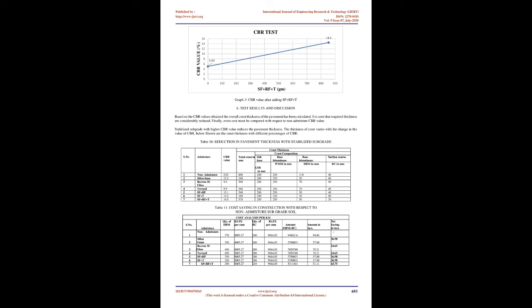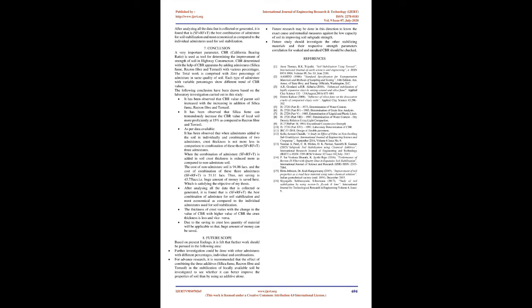The total work is compared with 0% of admixture in the same quality of soil. Each type of admixture with variable percentages shows a different trend of CBR values. The following conclusions have been drawn based on the laboratory investigation carried out in this study. It has been observed that the CBR value of parent soil increased with the addition of silica fume, Recron fiber, and Terrasil. It has been observed that silica fume can tremendously increase the CBR value of local soil more proficiently at 15% as compared to Recron fibre and Terrasil.